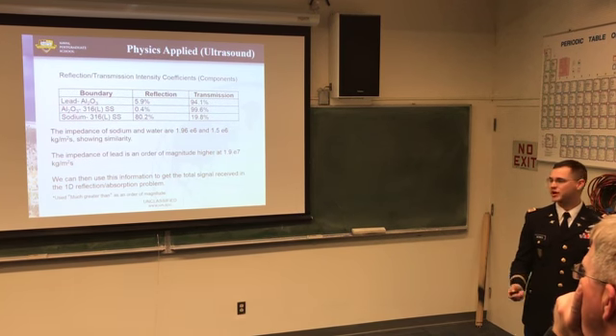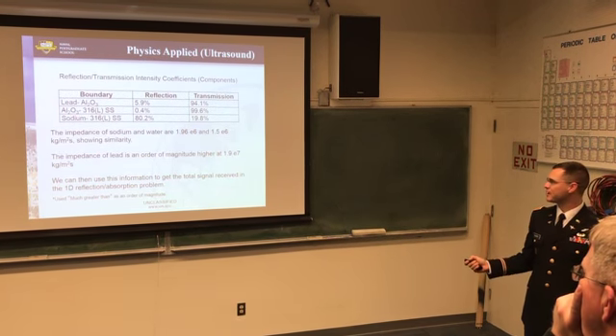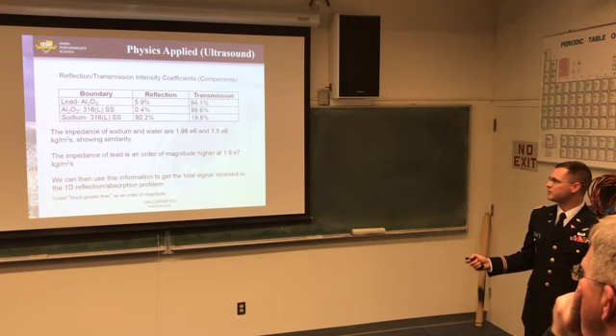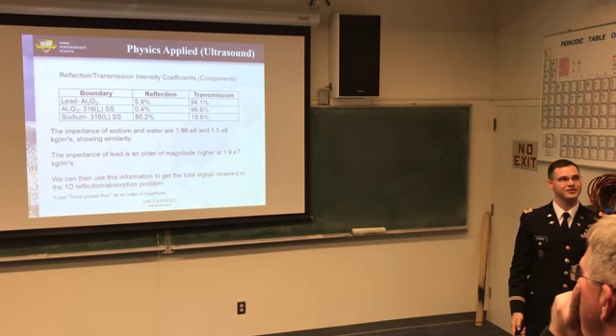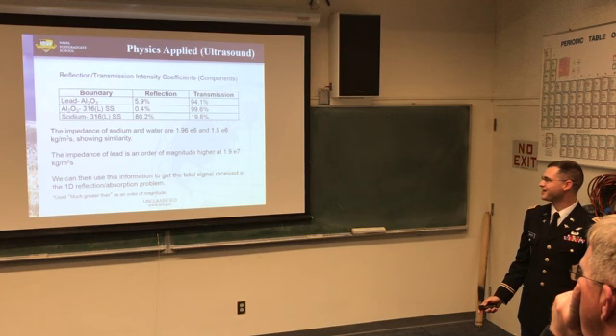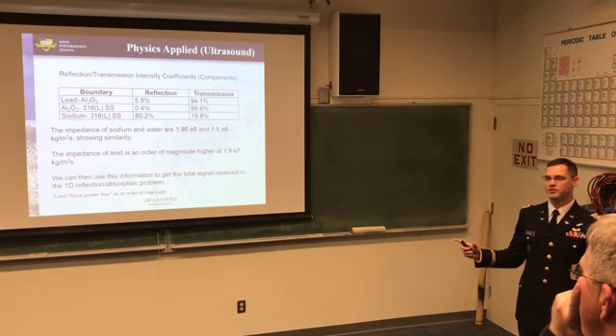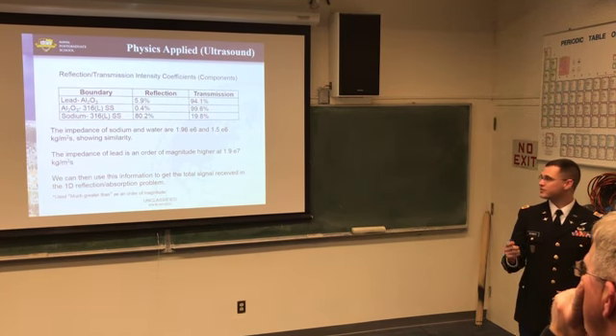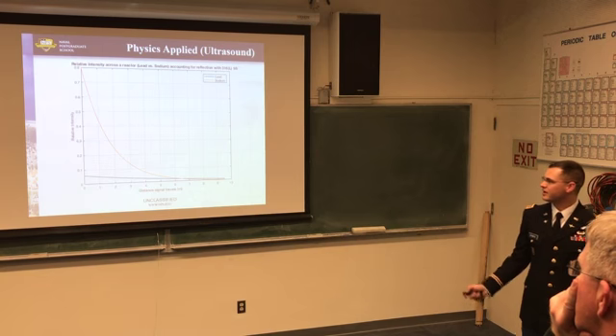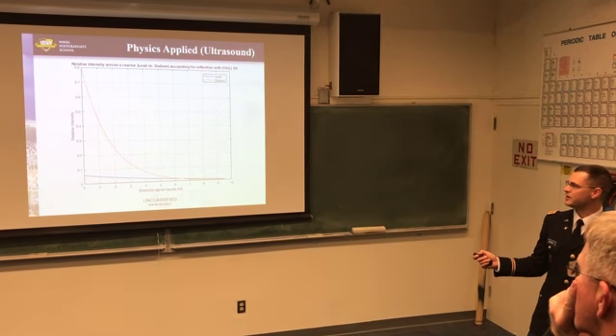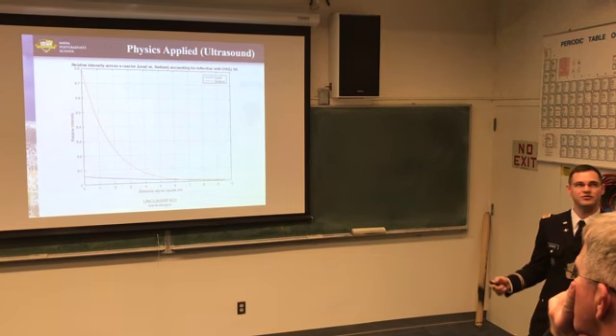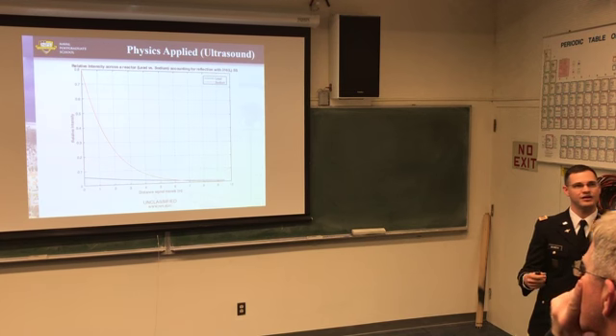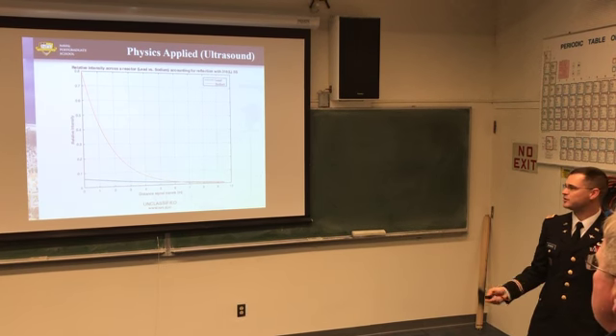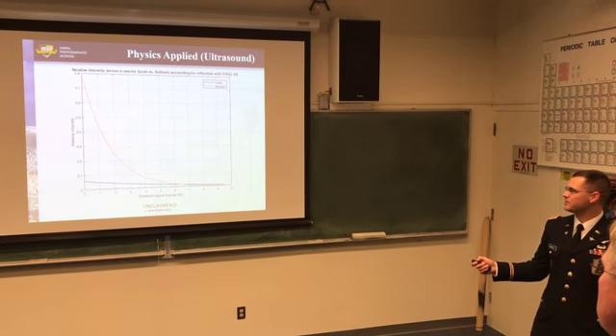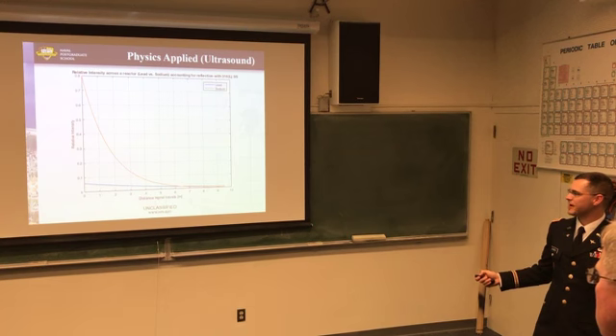At first we thought, okay, well, sodium is probably comparable, but sodium is about an order of magnitude less. So you get about 80% reflection. It's like, oh wow, I might run into a problem here. But when you combine this with the absorption coefficient, because sodium attenuates almost an order of magnitude more than lead, or the sound in sodium attenuates more than lead, the relative intensity drops off much faster.